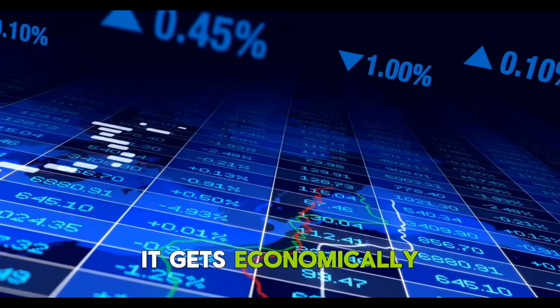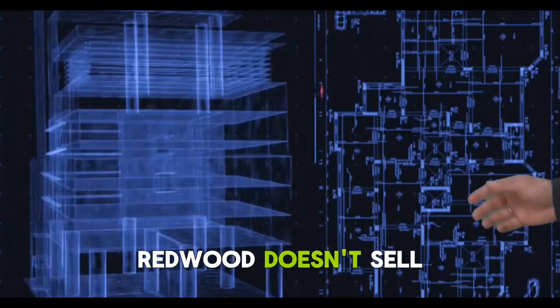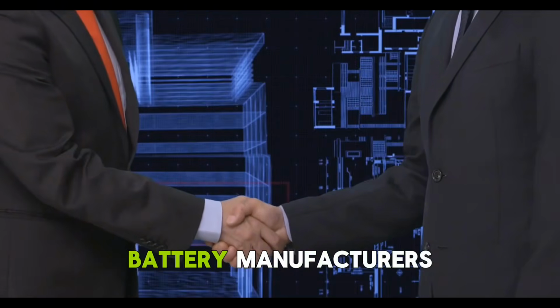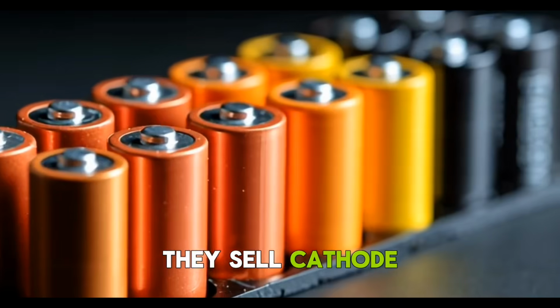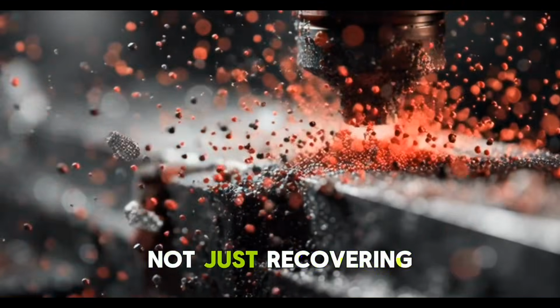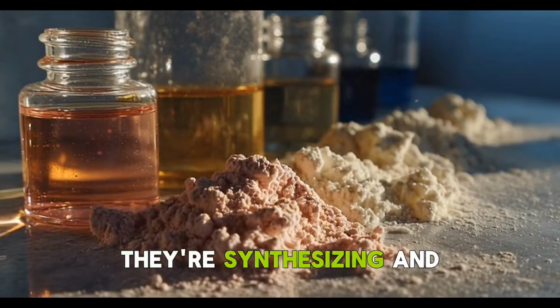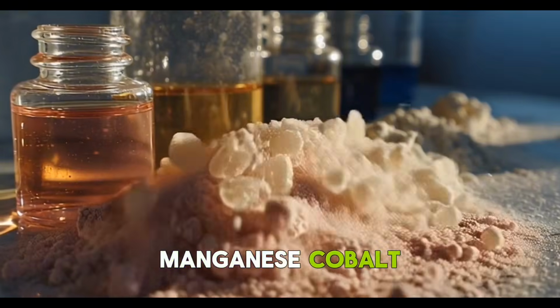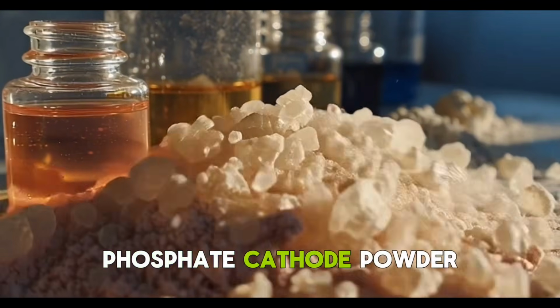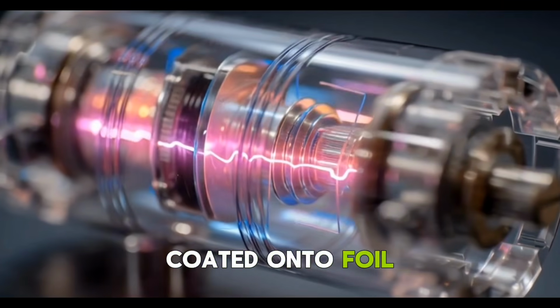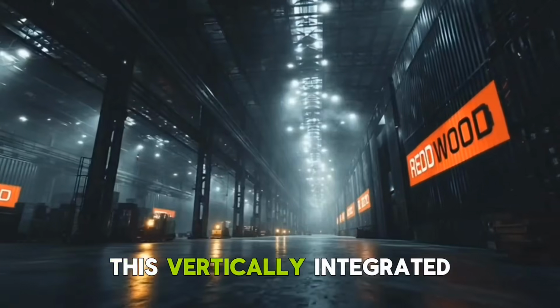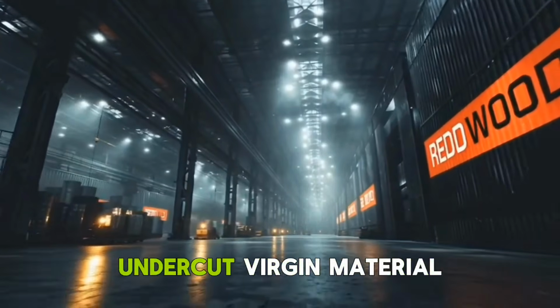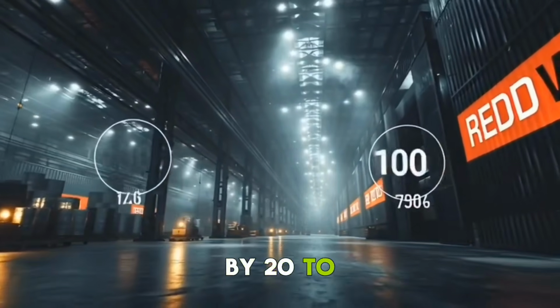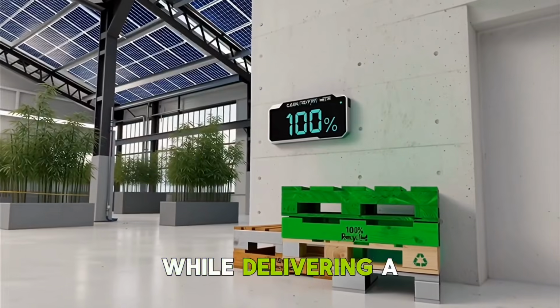And here's where it gets economically interesting. Redwood doesn't sell recycled lithium carbonate to battery manufacturers. They sell cathode active material. That means they're not just recovering raw lithium, they're synthesizing it back into nickel manganese cobalt or lithium iron phosphate cathode powder, ready to be coated onto foil and rolled into cells. This vertically integrated approach allows Redwood to undercut virgin material suppliers by 20 to 30% on price, while delivering a product with a 70% lower carbon footprint.